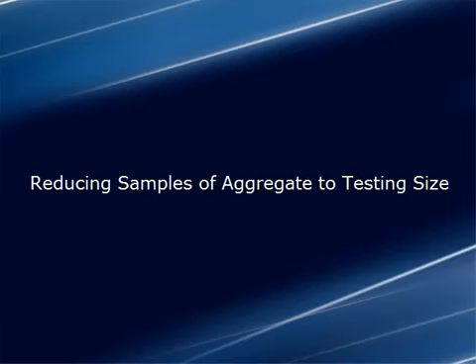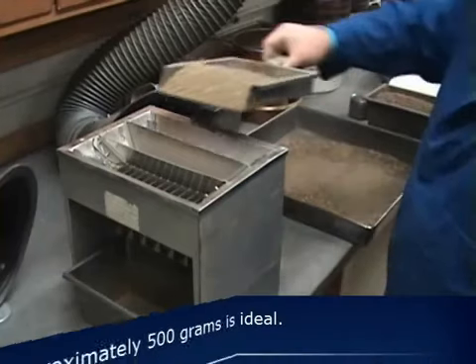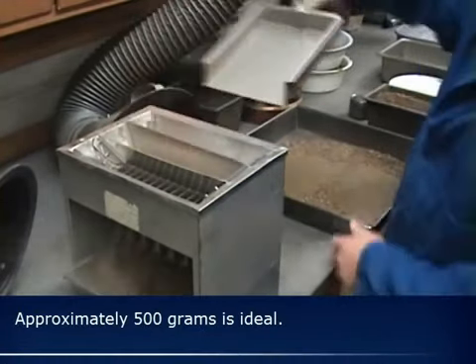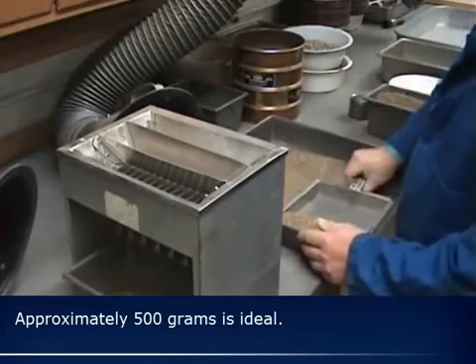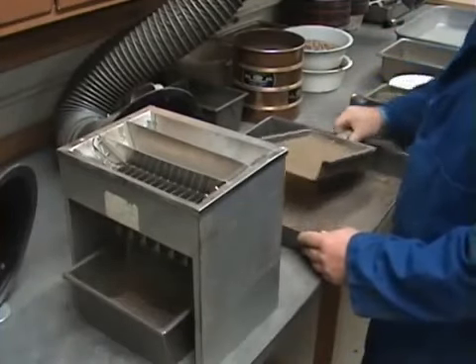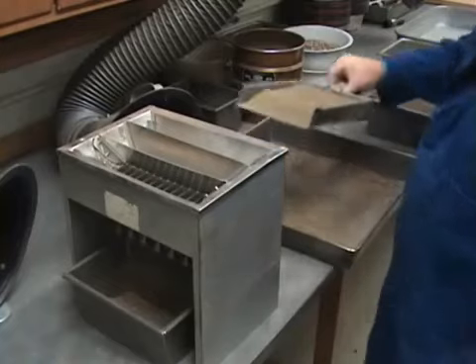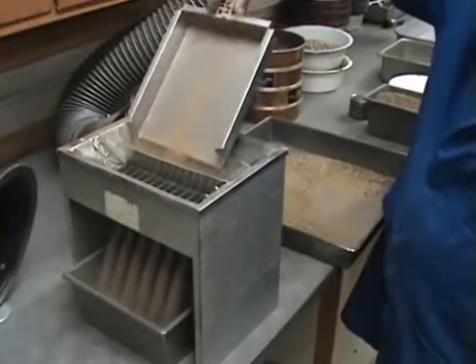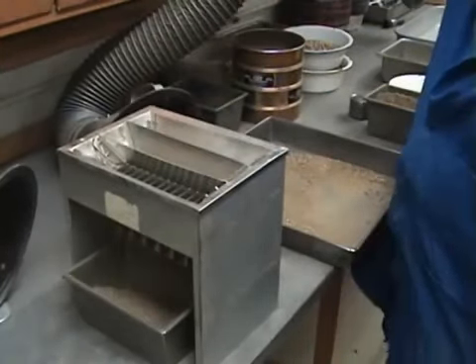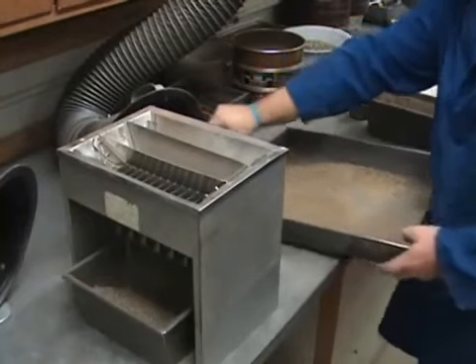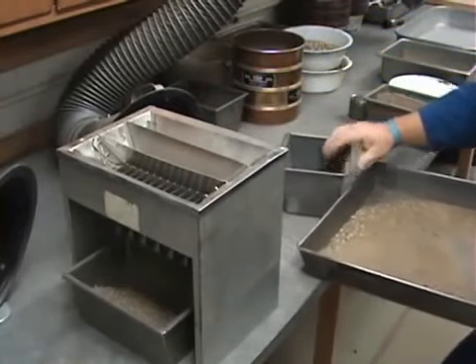Next, you reduce the fine aggregate sample to a testing weight. Reduce the sample to approximately 300 to 500 grams. It's important to obtain an approximate weight rather than an exact weight. The sample size needed is determined by your nominal maximum aggregate size. A table in the wash test procedure lists the minimum size needed.